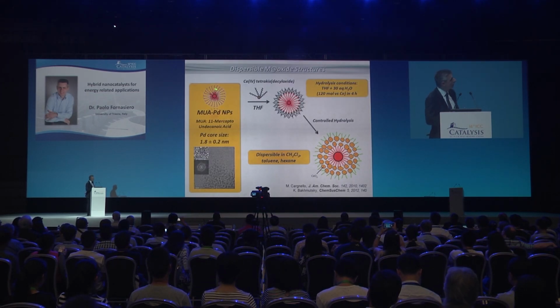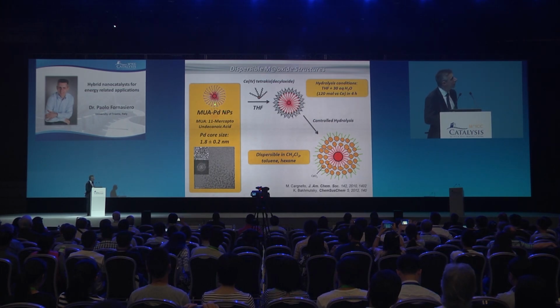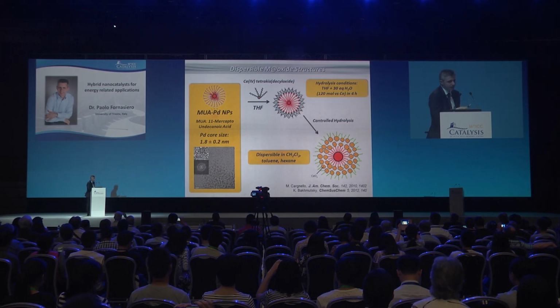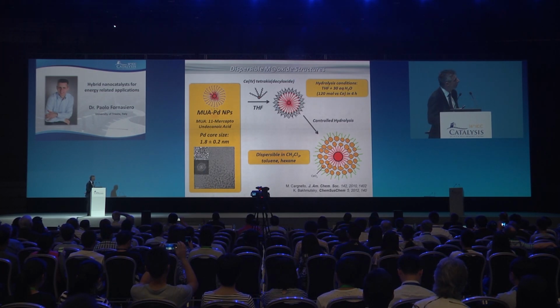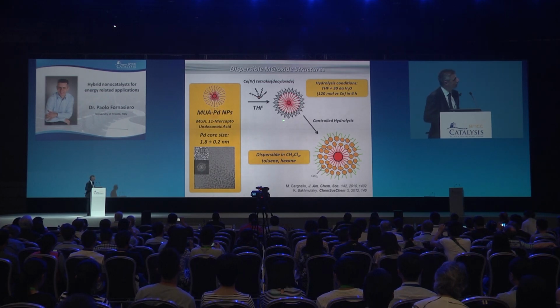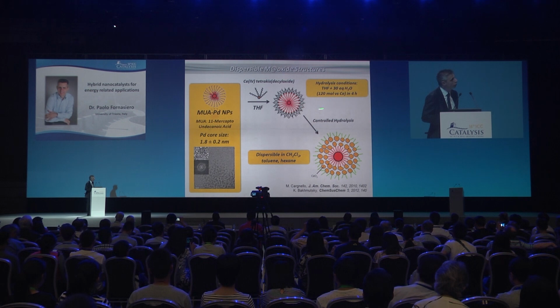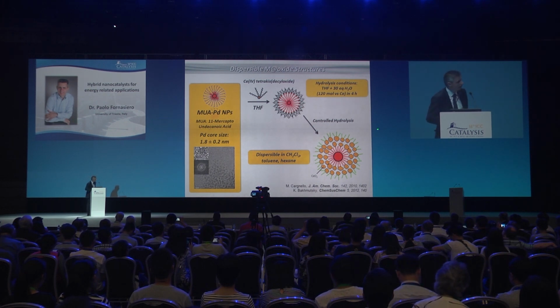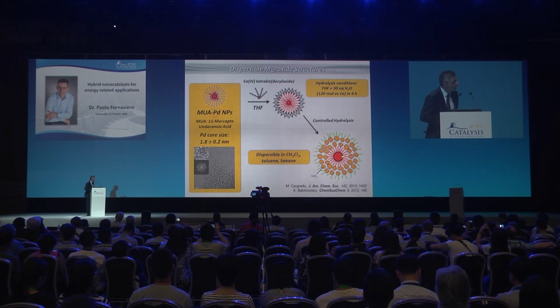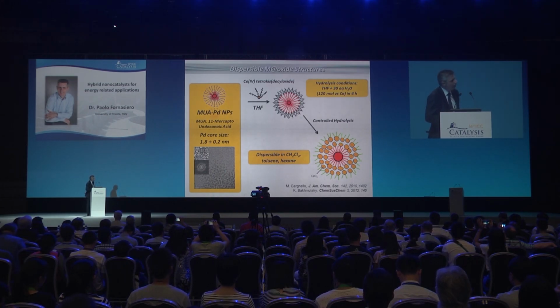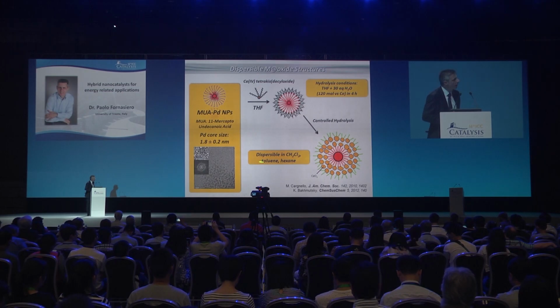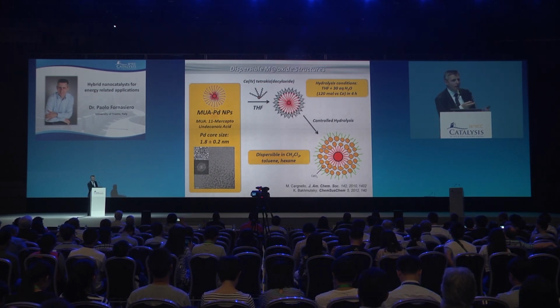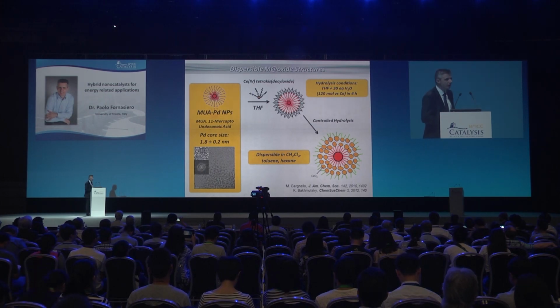So we prepare protected metal nanoparticles thanks to the strong interaction of thiols with palladium, but this is true also for platinum and gold, and we use acidic thiols which can coordinate a metal alkoxide in such a way that if you do a controlled hydrolysis in the presence of dodecanoic acid, you end up with this type of unit in which you have a metallic core surrounded by units of ceria, in this case, or cerium hydroxide. And thanks to these hydrophobic tails, these units are highly dispersible in organic solvents. So you can have this stable dispersion, and you can impregnate a stable scaffold.